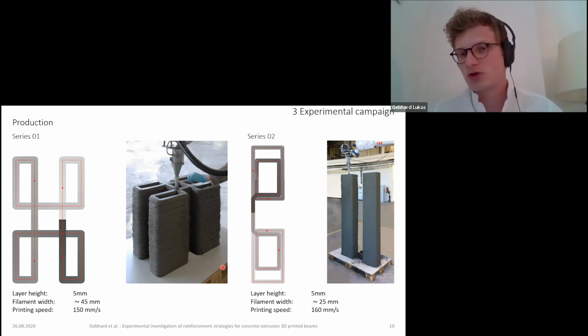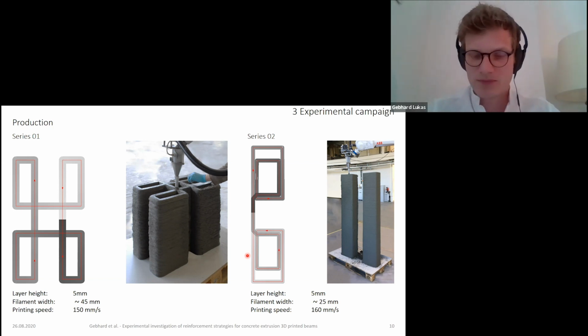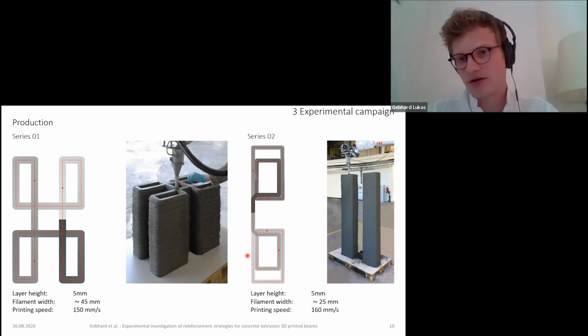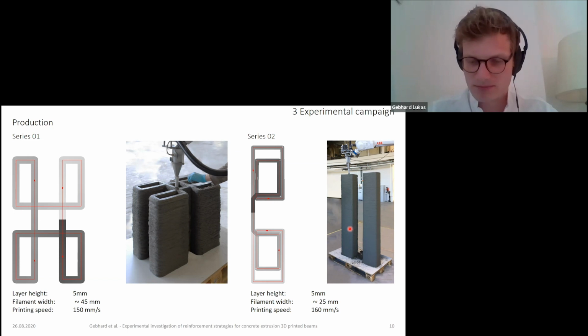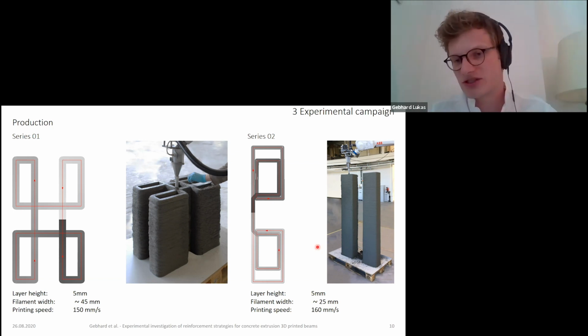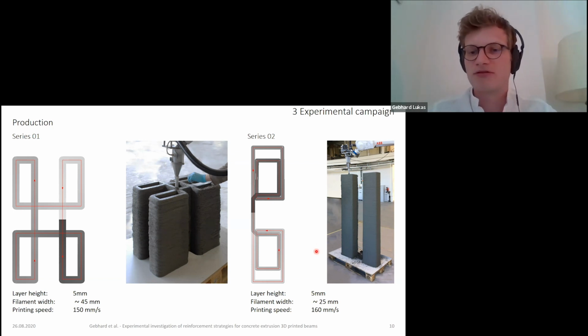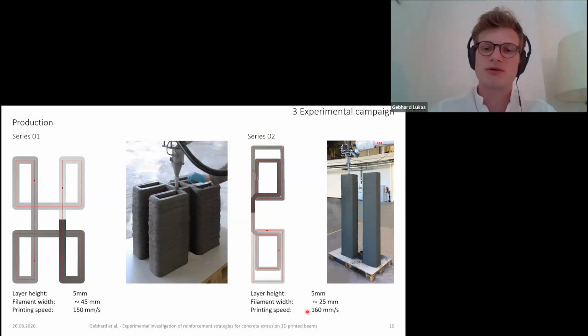The series 2 was produced by 2 filaments, and we did avoid the printing of only half beams. So we printed the entire beam in one go. Again, a set of an unreinforced beam and a reinforced beam. The layer height was the same with 5 millimeters, but the filament was reduced to 25 millimeters, and the printing speed was 160 millimeters per second.